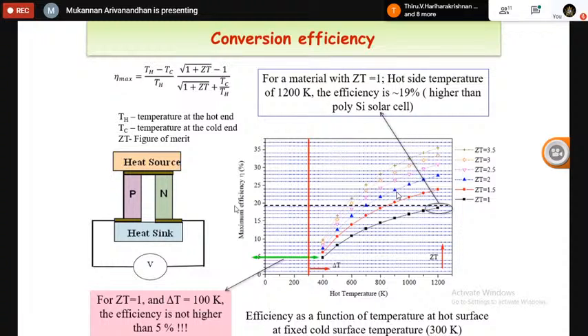Then if you want to improve the performance up to such a technology, you have to concentrate on the material property. And here you can see the conversion efficiency of a thermoelectric module. This conversion efficiency relation is a function of the temperature gradient as well as the figure of merit. Based on this relation, one can calculate the conversion efficiency as a function of two factors: one is the hot end temperature, and another one is the figure of merit. Here is the theoretically calculated data. Look at the data: my conversion efficiency is increasing as a function of temperature, as well as it is increasing as a function of figure of merit.